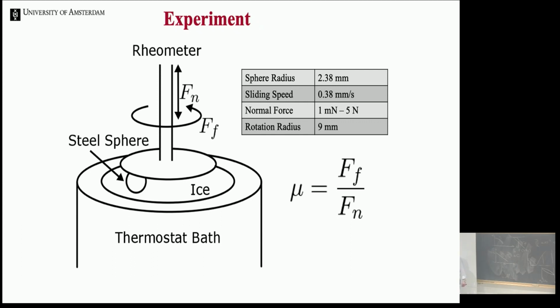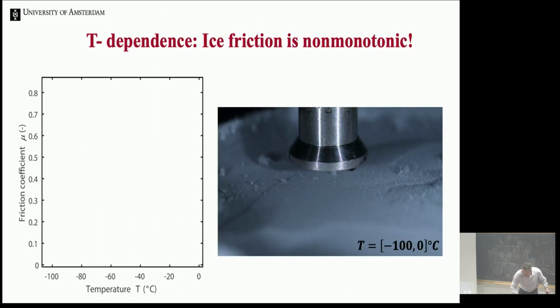Yeah, and so this is a friction machine, and it's a very cheap friction machine, because I already had it at the lab, and the importance is it's a very sensitive friction machine. And so I set out to measure the friction of the steel sphere on ice at very low temperatures, because my brother said something very interesting should happen. Yeah, and so this is the actual experiment. We film it here, so there's a layer of sort of ice crystals that have nucleated on the surface, but normally we close everything off, and we do that under a very low humidity, and then we have very nice ice. And so, ta-da, yes?